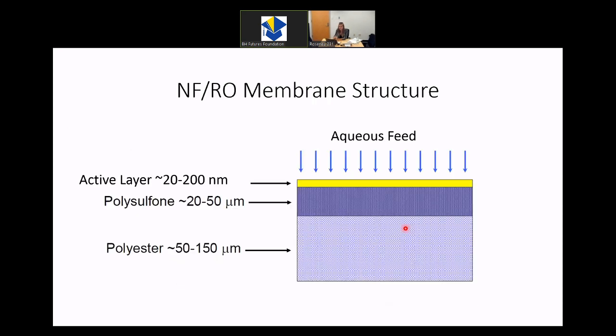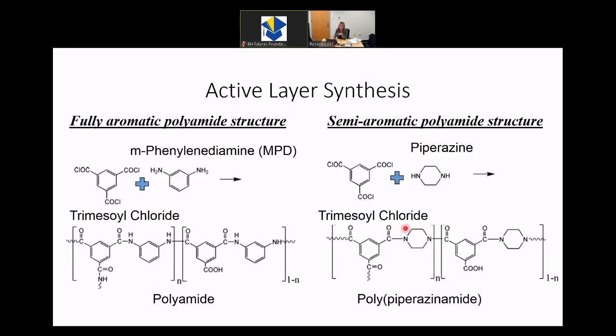So in terms of preparing, we're going to go back a slide here. In terms of preparing that top yellow layer, the active layer, that's the layer that's the main contaminant rejection. That's the layer that is most responsible for cleaning your water. So there are two common active layer synthesis procedures to make this top layer, and one of them is fully aromatic, and one of them is semi-aromatic. And the difference there is that both of them use this trimesoyl chloride monomer here, but what it's reacted with is a little different. So here in the fully aromatic polyamide structure, you react it with something called m-phenylenediamine, MPD. And on the other one, the semi-aromatic polyamide structure, you react it with something called piperazine.